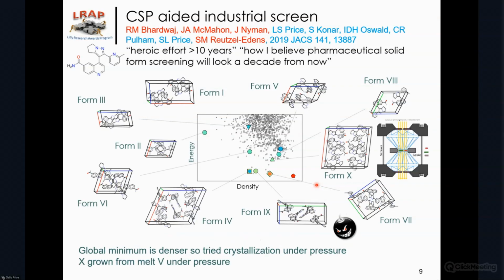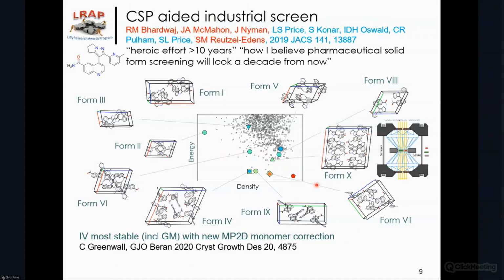There is still the denser global minimum. So they commissioned Colin Pulham in Edinburgh to try crystallizing this under pressure. And that did find one more polymorph, mainly because the pressure enabled Form 5 to be melted and then recrystallized. It still hadn't found the global minimum. After we published it, Greg Beran used a really good calculation on the monomer correction and showed that actually the known Form 5 was more stable in lattice energy than our global minimum.